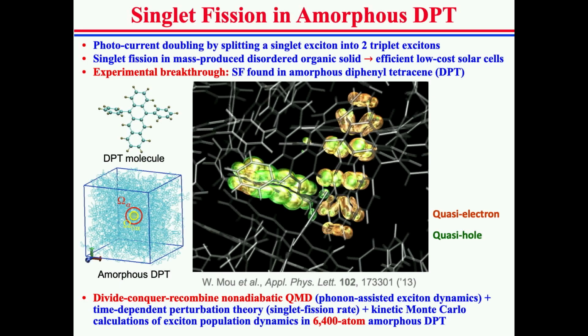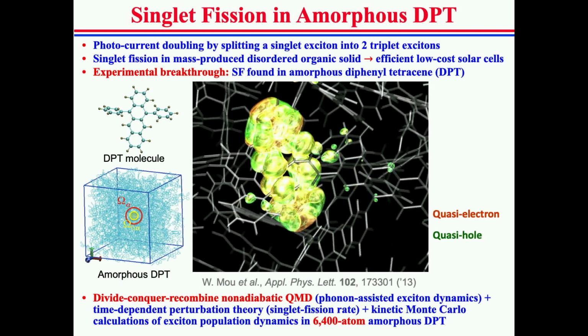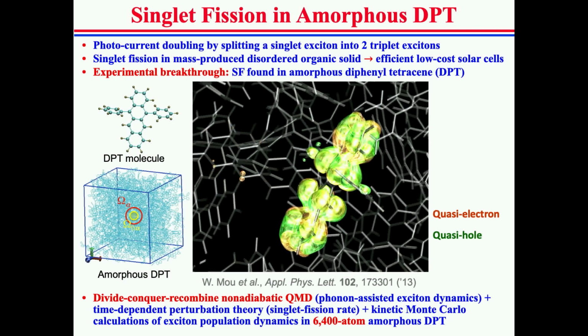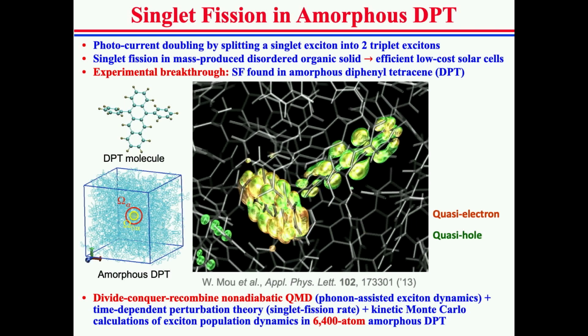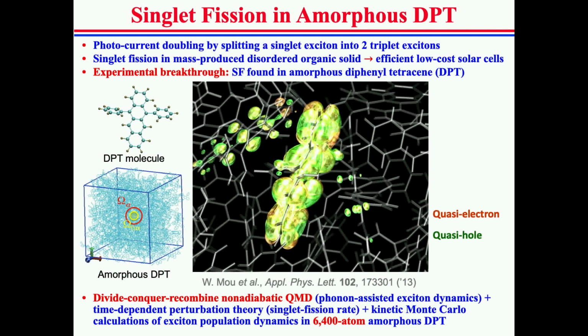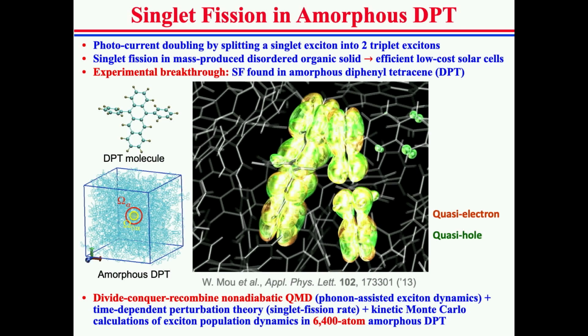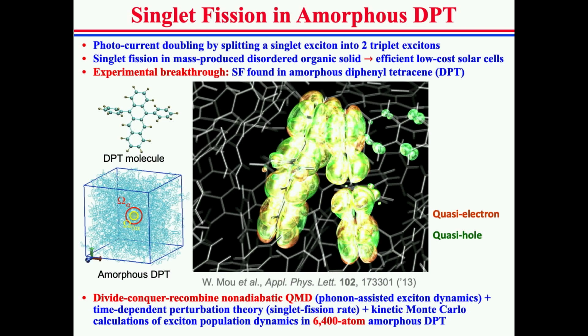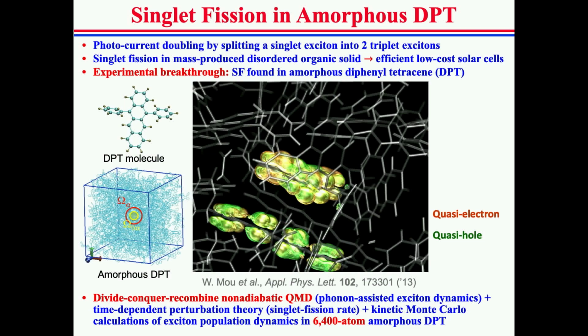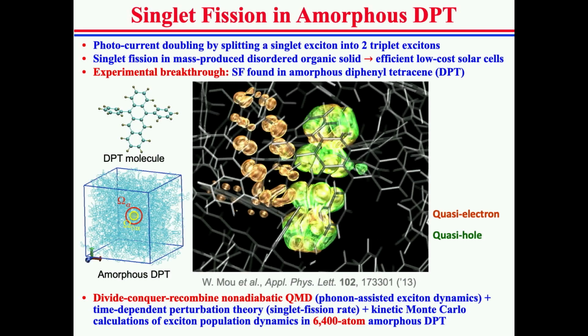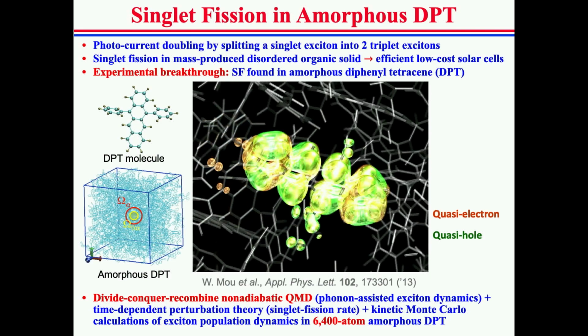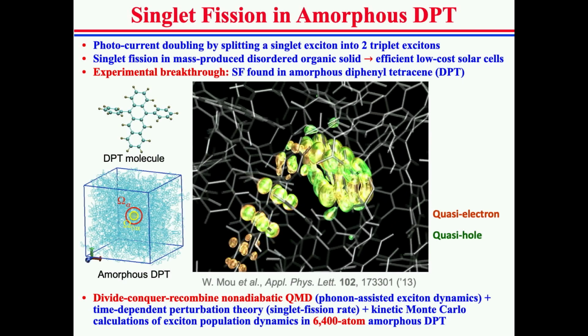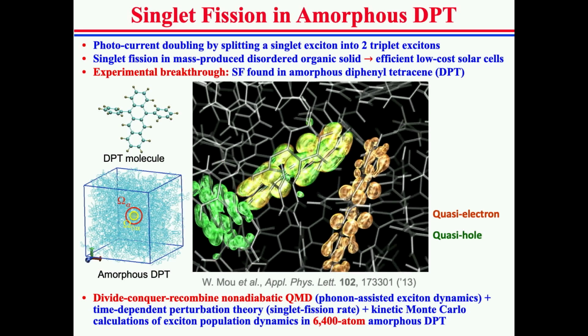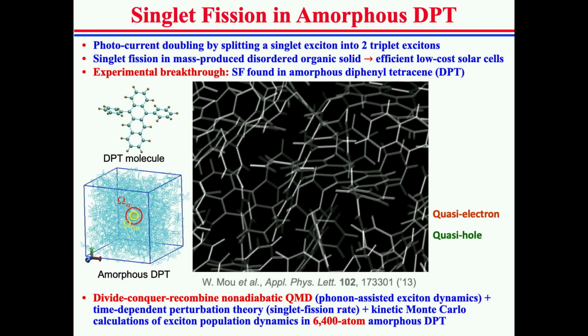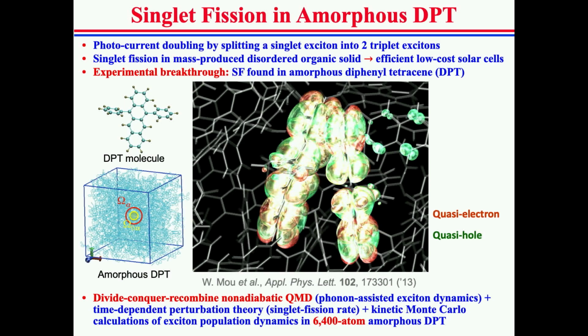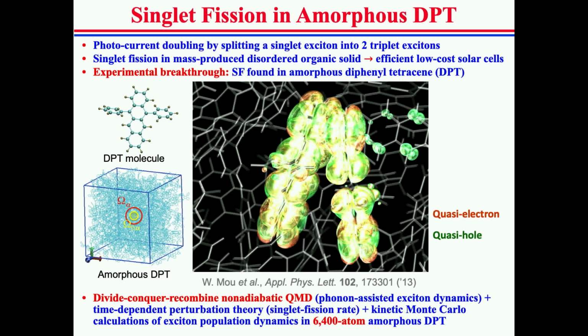This is an example of divide-and-conquer-recombine non-adiabatic QMD. We studied singlet fission in amorphous diphenyl tetracene. Absorption of a photon creates one singlet exciton, an electron-hole pair. But the photocurrent can be doubled by splitting the singlet exciton into two spin-triplet excitons. This is called singlet fission, but singlet fission has been limited to perfect, very clean crystals. But if a high singlet fission yield is achieved instead in a disordered solid, which is cheap to mass produce, we will have an efficient and low-cost solar cell.